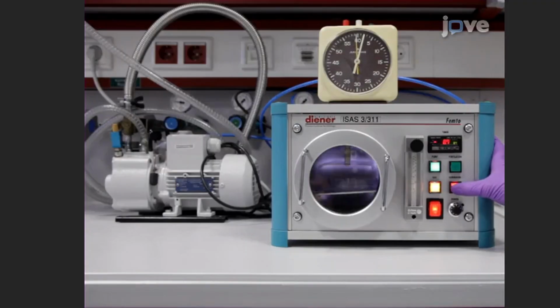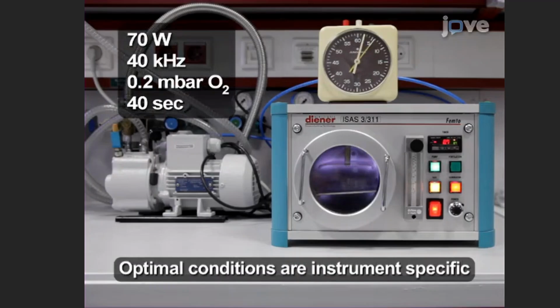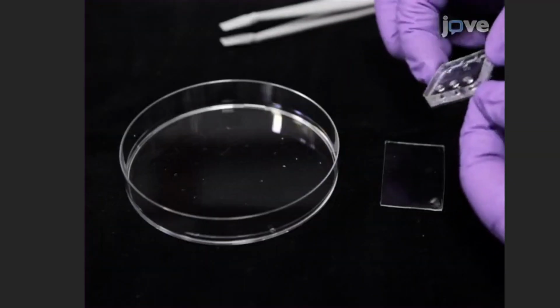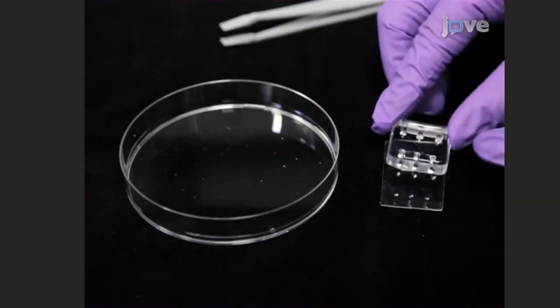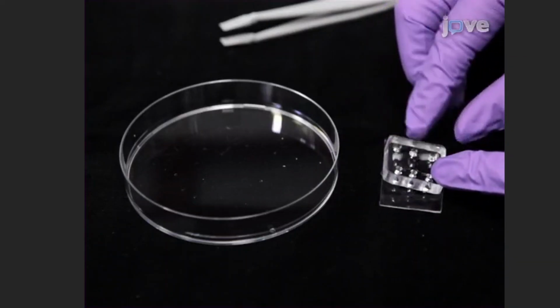Shortly after cooling, and while wearing safety glasses, use a scalpel to prise the cover slip PDMS bilayer from the petri dish. To encapsulate the device, a good PDMS-PDMS bond is needed. Place the PDMS bilayer and the microfluidic device in the plasma oven for 40 seconds. Once plasma treated, press both parts together and allow to fully bond.